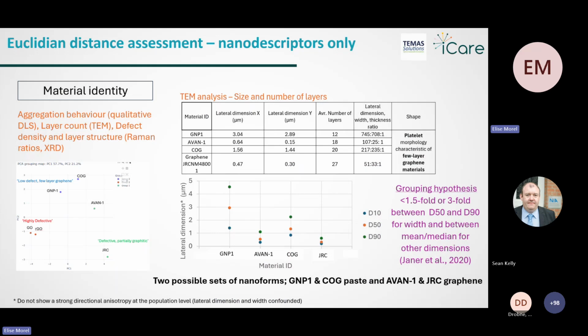Yeah, for the moment we are still in the process of incorporating the data from the different partners, which is quite time consuming. But if we do really basic Euclidean distance assessments on some of the materials for which we have data, we can see that we already have two sets of nanoforms formed when you take into account qualitative DLS data, because it is not applicable quantitatively for graphene, but several experiments in different media were used to be categorized and input in there. The layer count from the TEM data, defect density and layer structure from Raman ratios and XRD.